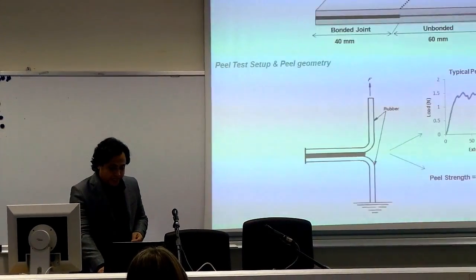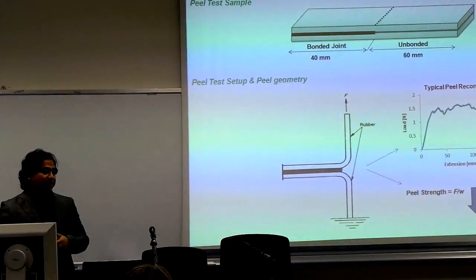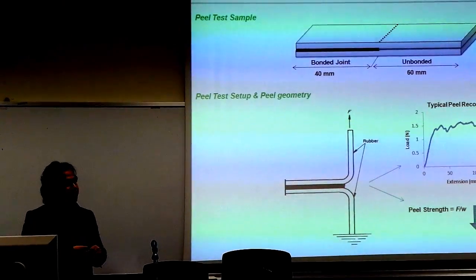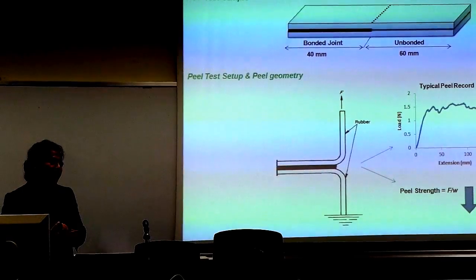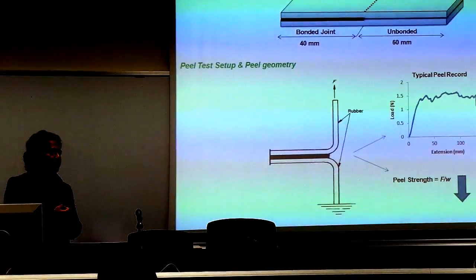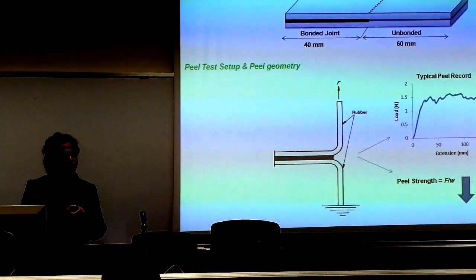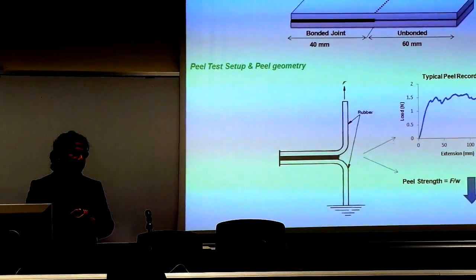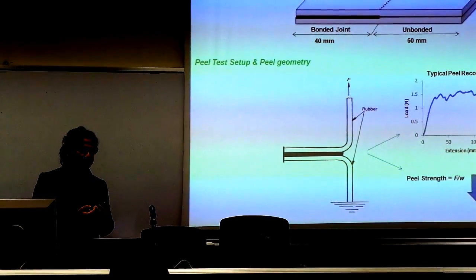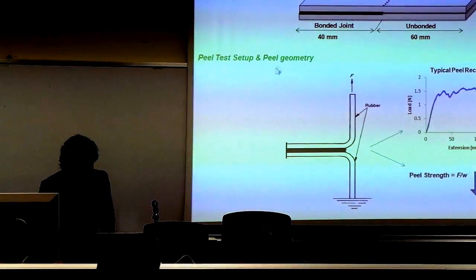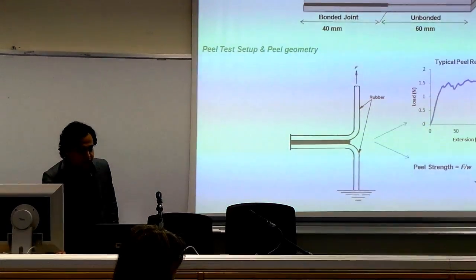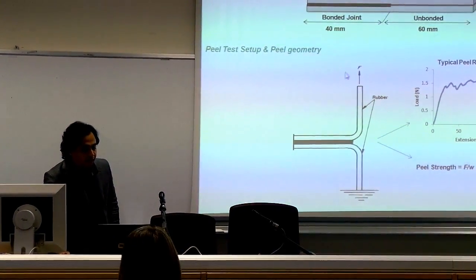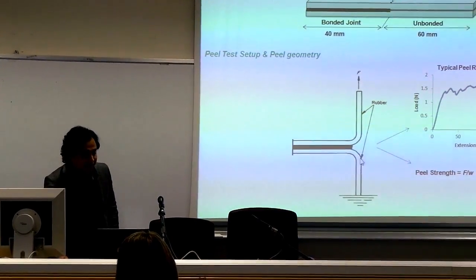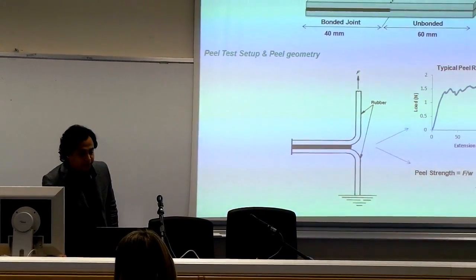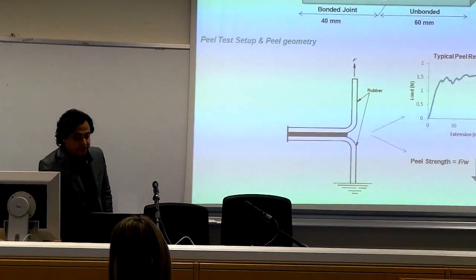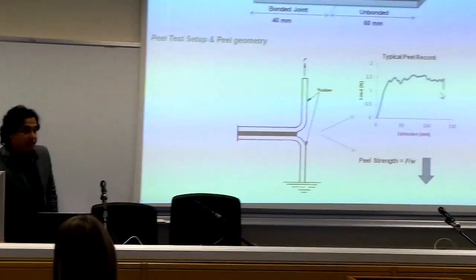And this is why I studied the self-healing behavior of epoxidized natural rubber. Since the epoxidized natural rubber at room temperature is very sticky in nature, I tried to understand their adhesion behavior. And to do that, I performed the peel test, which is a conventional way to understand the adhesion strength in the rubber. You can see the generalized sketch of the peel specimen. And the peel test was done in T-peel geometry. This is the typical peel record that I obtained from the peel test. And peel strength was calculated from this peel curve.